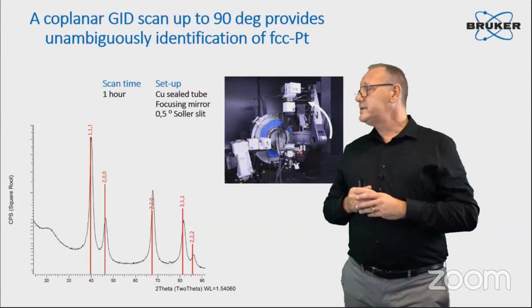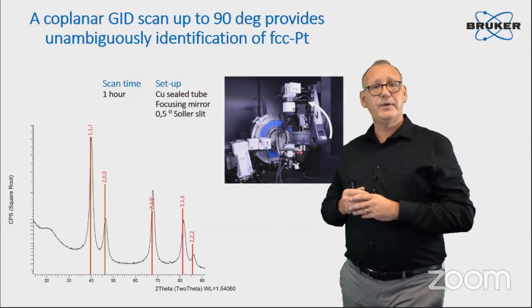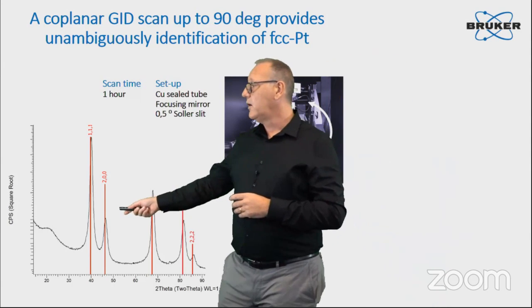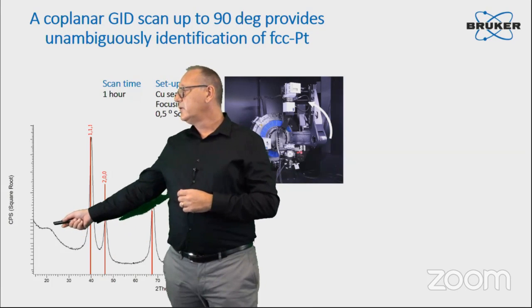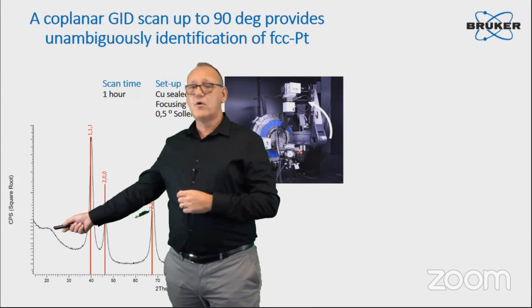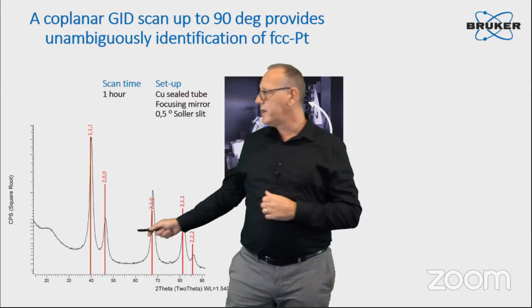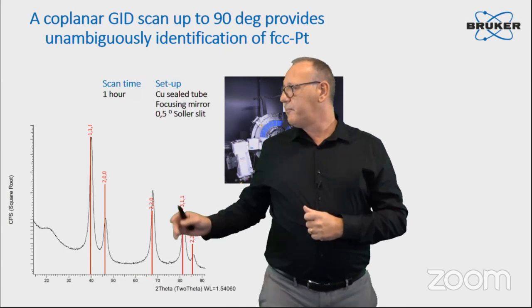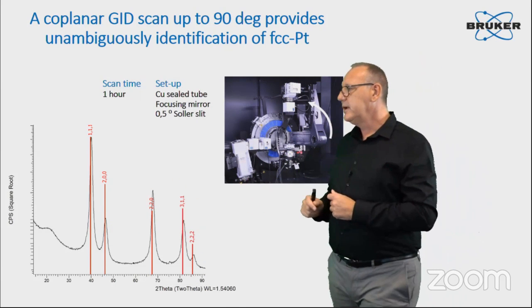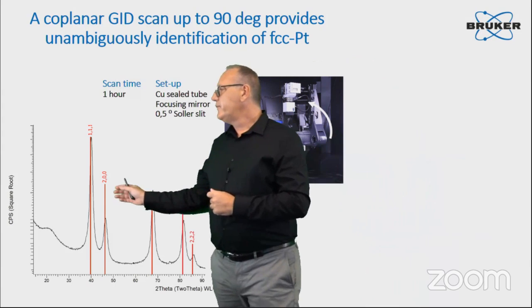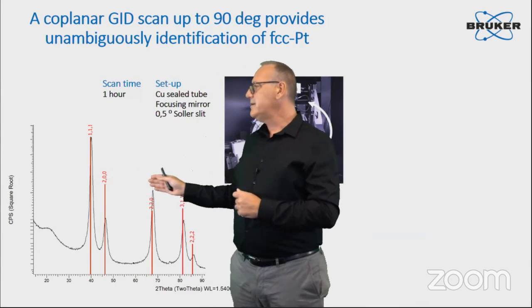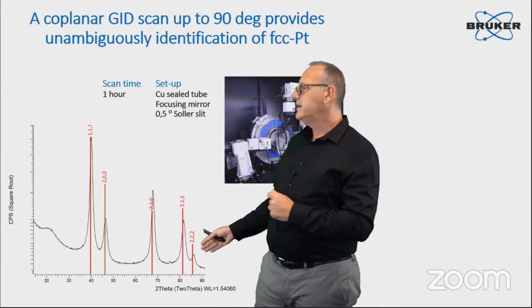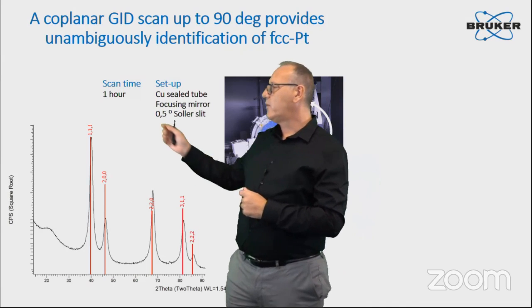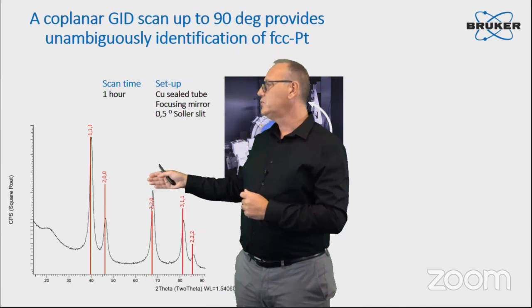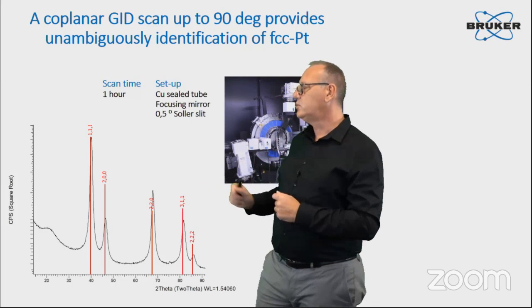So what do we see here? By the way, you see that even if it's only 10 nanometer, the glass signal has almost vanished. So I think we have nicely optimized the conditions here. Incident angle is around ½ degree. And what we see is that the peaks we observe nicely match with the FCC peaks of platinum. We have all peaks: 111, 200, 220, 311, and 222.